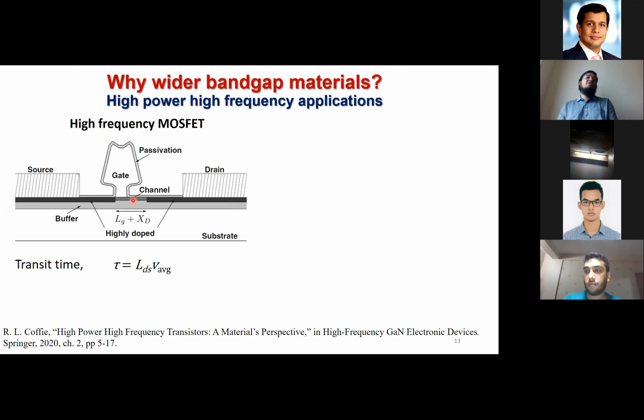So now, if you want to minimize this transit time or increase the frequency, we can define tau min, which for a fixed length L_DS, uses the maximum velocity a carrier can achieve in the channel, the saturation velocity of the material, which is again a fixed material parameter. So this is the minimum transit time we can achieve for a given channel length. So now this works only for the higher frequency.